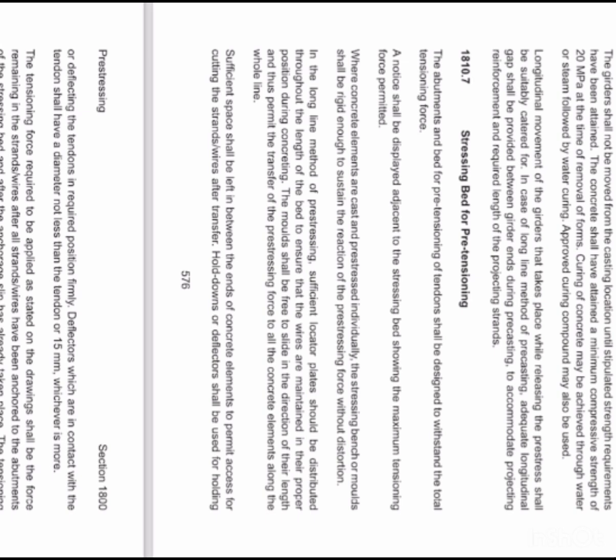Deflectors which are in contact with the tendons shall have a diameter not less than the tendon or 15 mm, whichever is more. The tensioning force required to be applied as stated on the drawing shall be the force remaining in the strands wires after all strands wires have been anchored to the abutments of the stressing bed and after the anchorage slip has already taken place. The tensioning force shall be determined by direct reading of the pressure gauge or dynamometers and by the measured elongation after slip.